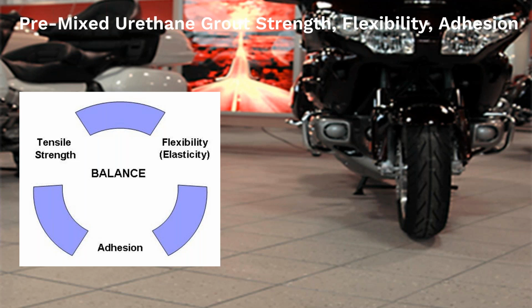So with pre-mixed urethane grout, we do talk about strength, flexibility, and adhesion. So there is that balance between the tensile strength, the flexibility, and the elasticity of it, as well as the adhesion. So it is semi-flexible. There's low shrinkage, which leads to that high crack resistance we've been talking about throughout the presentation. And these balanced properties are really ideal for applications in industries such as the automotive industry, where you see the setting of the motorcycle as in this picture on the floor.